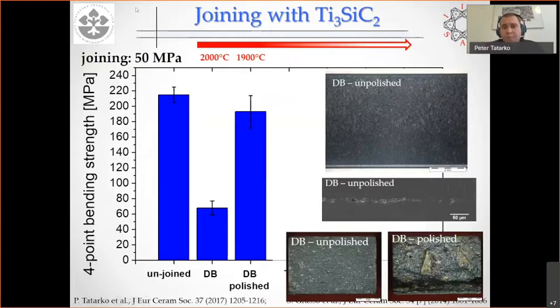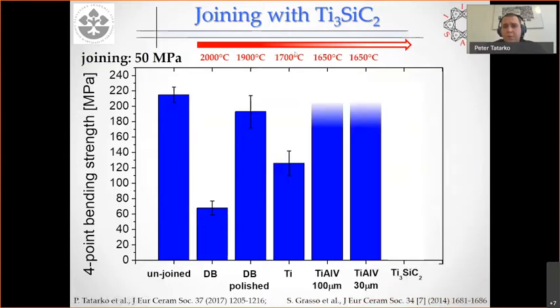So the problem was the temperature. These processes require very, very high temperature. So we wanted to reduce the temperature, and we used titanium and titanium aluminum vanadium foils. You can see we could lower the temperature to 1700 for titanium or 1650 for titanium aluminum vanadium. And especially for the titanium aluminum vanadium, we got very nice strength which reached that of the reference unjoined material.